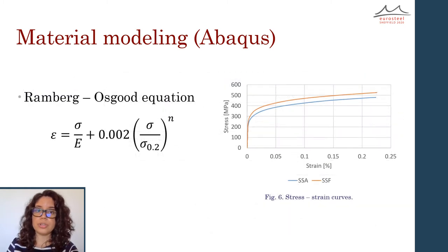Moreover, using the values of the previous slide, the material stress strain curves were modeled using the Ramberg-Osgood equation to simulate the plastic nonlinear behavior of stainless steel.